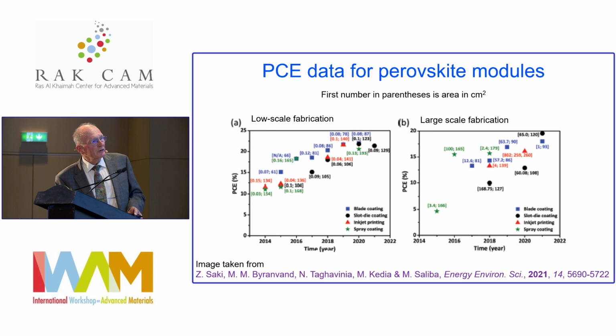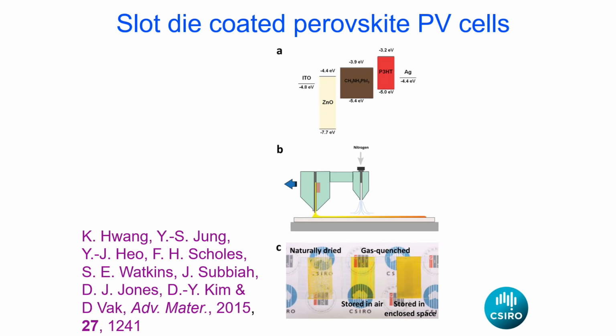reach those efficiencies. In our own case, in our own consortium, the best result we obtained in 2015 was through slot die coating of a perovskite onto a glass substrate, not a flexible substrate. Here you see the image of the slot die coating. And I'll show you the assembly, but here you see the components. We had zinc oxide, we had the perovskite, methyl ammonium lead iodide, and poly-3-hexylthiophene as that P donor material.